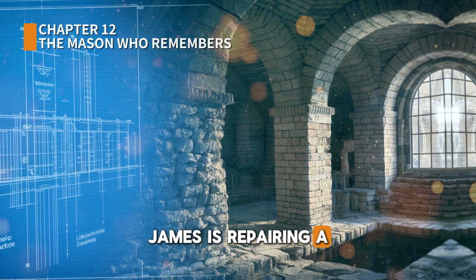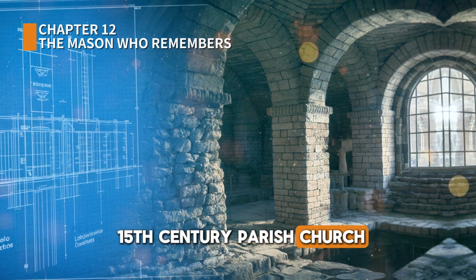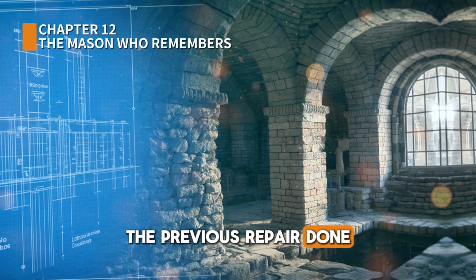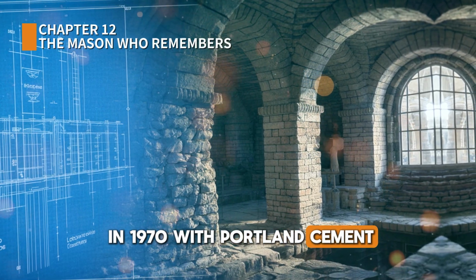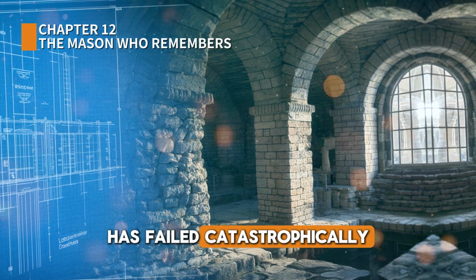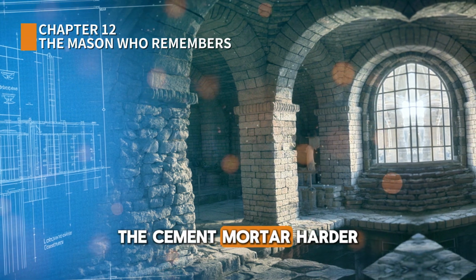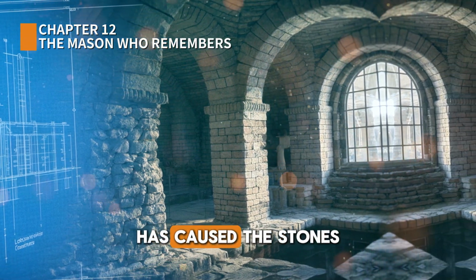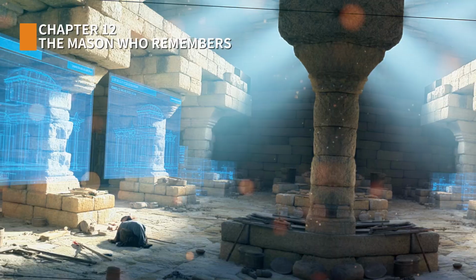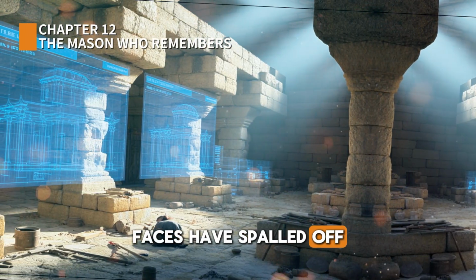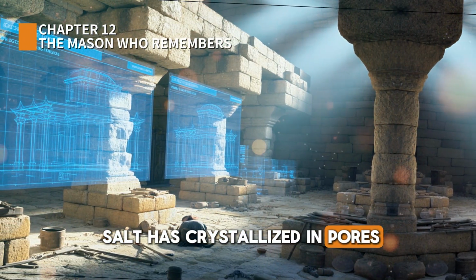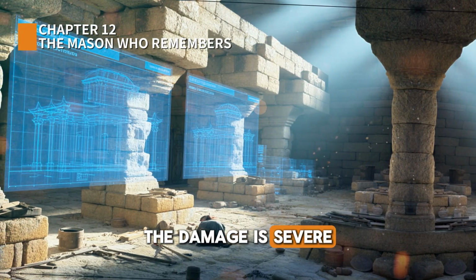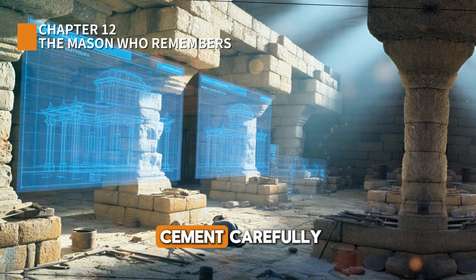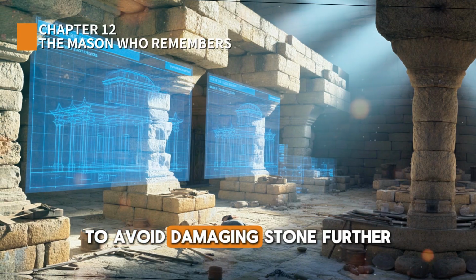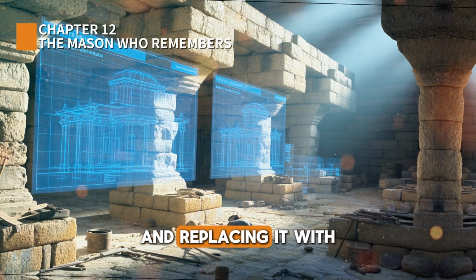James is repairing a 15th century parish church. The previous repair, done in 1970 with Portland cement, has failed catastrophically. The cement mortar, harder than the stone, has caused the stones to deteriorate. Faces have spalled off. Salt has crystallized in pores. The damage is severe. James is removing the cement carefully to avoid damaging stone further and replacing it with lime mortar matching the original.